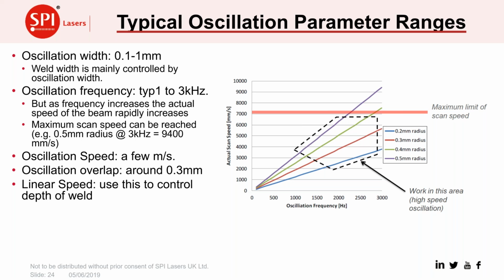So some typical ranges for those parameters. We might use something like 0.1 to 1 millimeter for the oscillation width, which is going to control our weld width typically. We might be running oscillation frequencies, well, let's say 1 kilohertz to 3 kilohertz, maybe sub kilohertz, a few hundred hertz as well sometimes. The oscillation speeds will then come out as a few meters per second. The overlaps may be 0.3 to 0.5 millimeters. And then we are using the linear speed to control the depth of the weld.